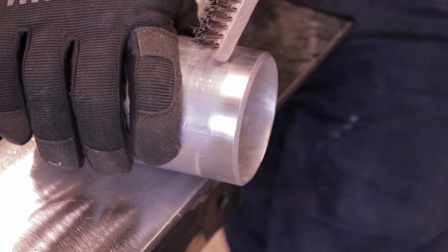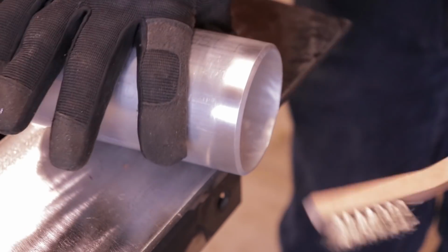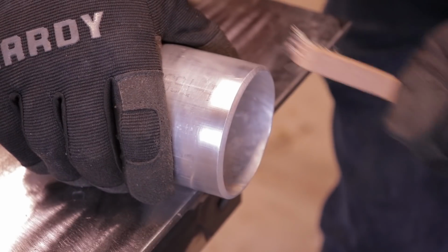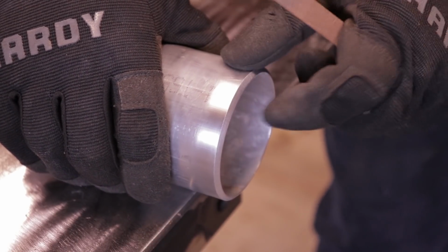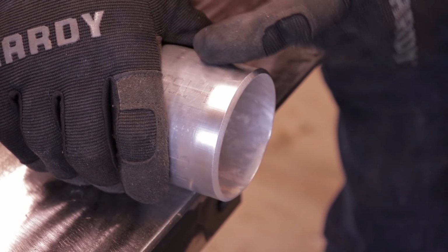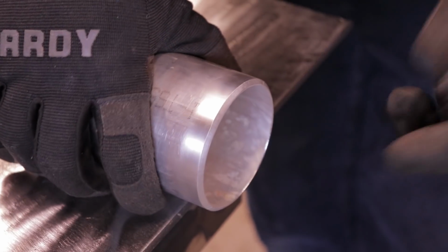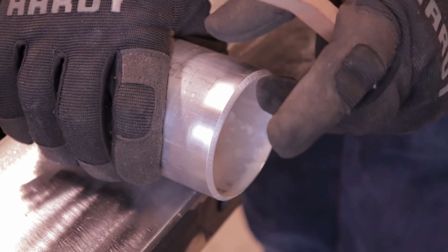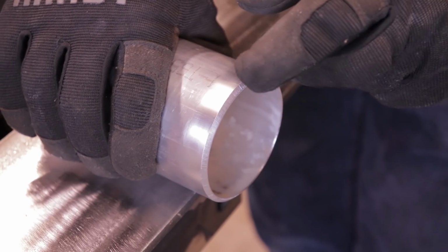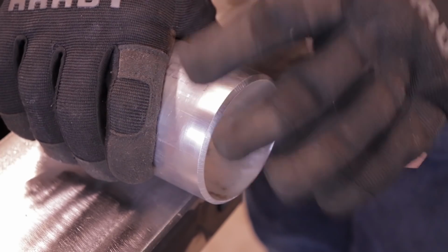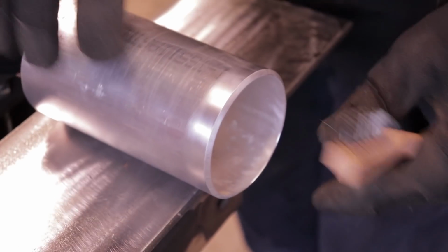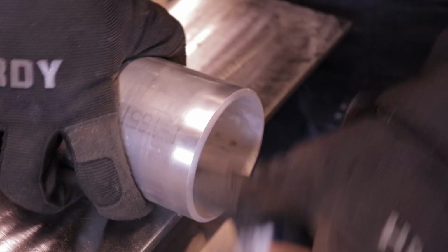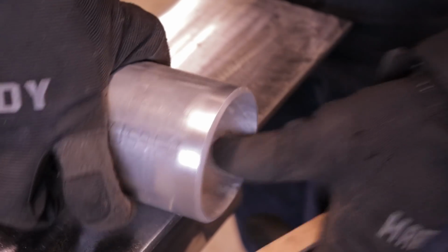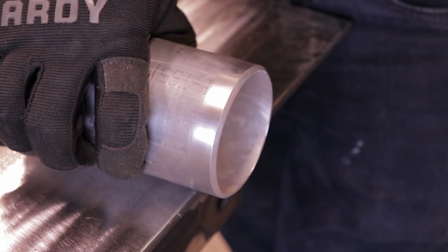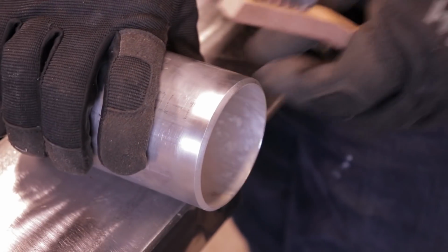6061, if I remember right, the tensile strength on it is something like around 40,000 psi. But when it's welded, in the heat affected zone, because it's a heat treated alloy, it takes the tensile strength down a lot. I think it's like 25 or 28,000 psi. So even though you're using 5356, and I think the tensile strength rating is like 30,000,